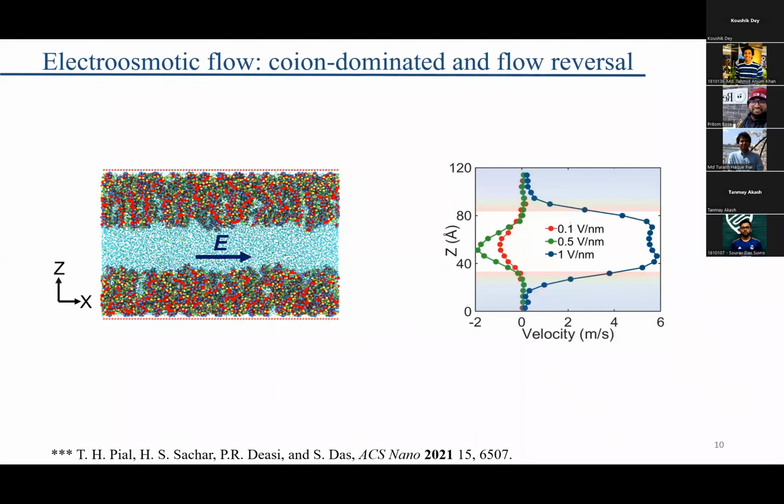But your question is very interesting, because inside a polyelectrolyte chain layer, deep inside the brush, you have very little water. Researchers have shown that the charge environment changes when you have a polymer in the bulk versus a highly crowded system. If you have water, your dielectric constant is very high, but if you don't have water, your dielectric constant is low. A low dielectric constant means your system won't try to be charged. Let's say all my polymer was same charged, but here it will be very difficult for all of the polyelectrolyte to be charged, because you have very little water.